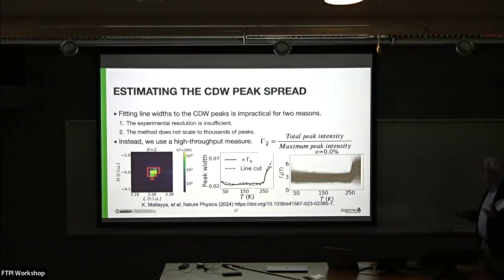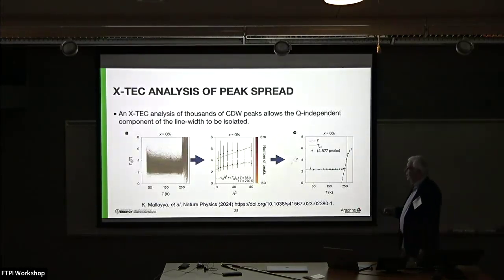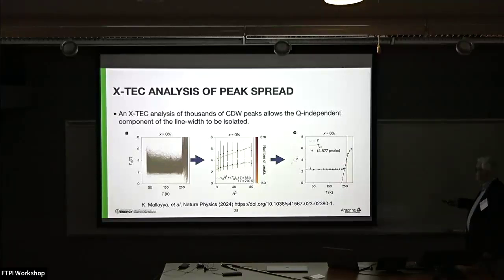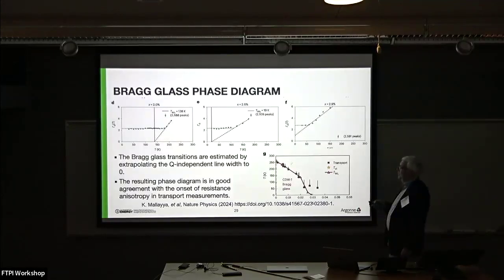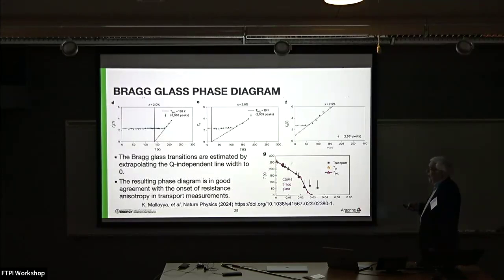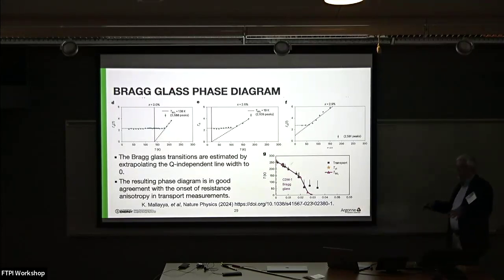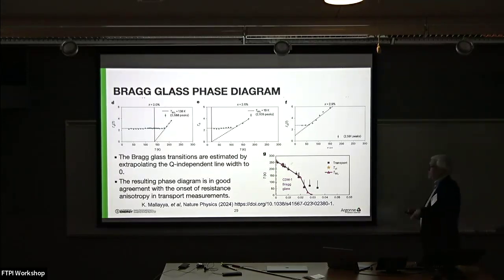And they did some benchmarking using more conventional techniques, and showed that this really did work. And so now you can actually analyze the line widths using X-TEC, using supervised machine learning, and identify what is the Q independent term in the widths. And so here you see that the line widths diverge as you expect with the pristine compound. But if you look at the other composition, if you go too high, then they saturate because too much intensity is leaking out of these peaks, but in a region above the resolution limit, you get this very clear temperature dependence, which actually seems to be linear.